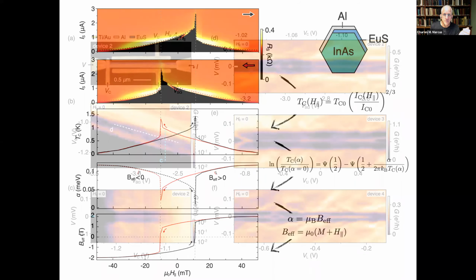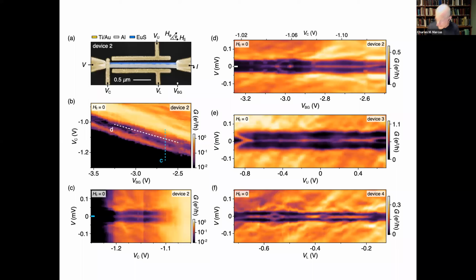Now, what happens spectroscopically is the interesting part of the story. What happens spectroscopically, we do by doing a different kind of geometry. Instead of putting 4 wires on this, we remove the superconductor at the end. Although we leave the europium sulfide on, we have to remove the superconductor but not etch the europium sulfide, and then put a gate across the end of the device.